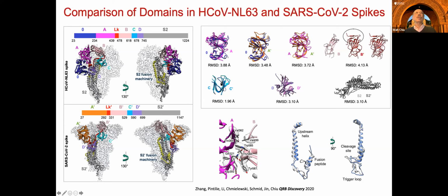And the other interesting analysis of our work is that in this C domain, one of the 4 or 5 domains of coronavirus, is both sequence and structurally highly conserved. So this leads us to suggest that perhaps if we want to develop a neutralizing antibody, this is the domain one should target, because you want an antibody that will kill not only COVID-2, but all coronaviruses in the entire family. And so this is one approach that we tackle this coronavirus particle.